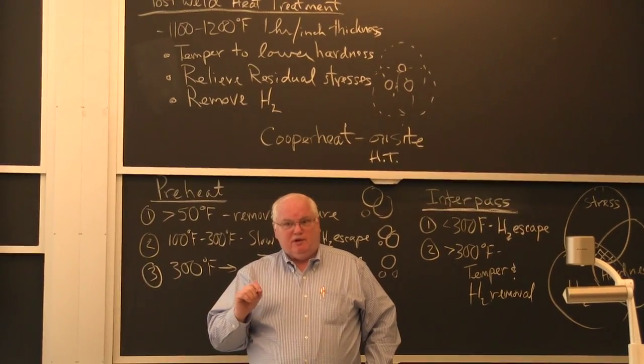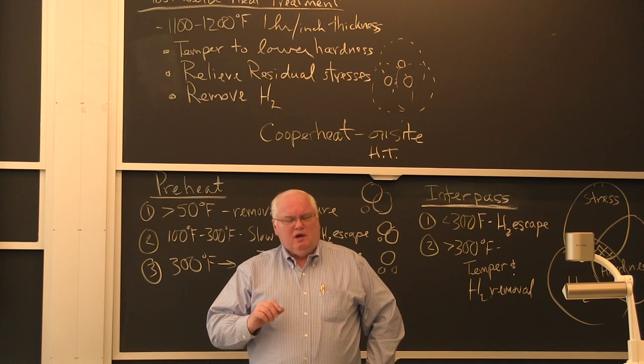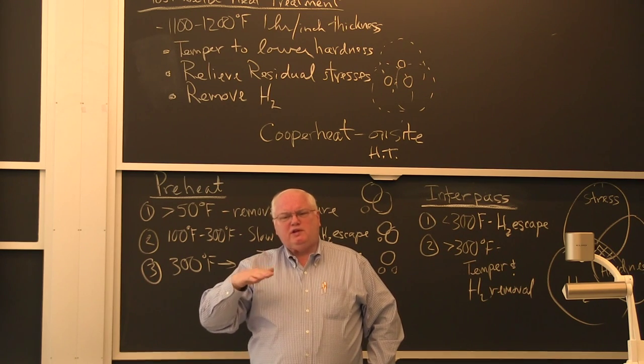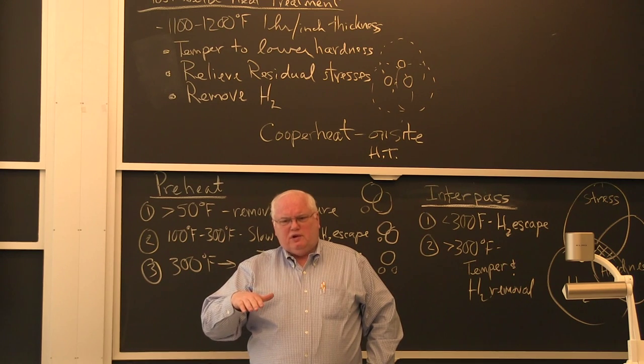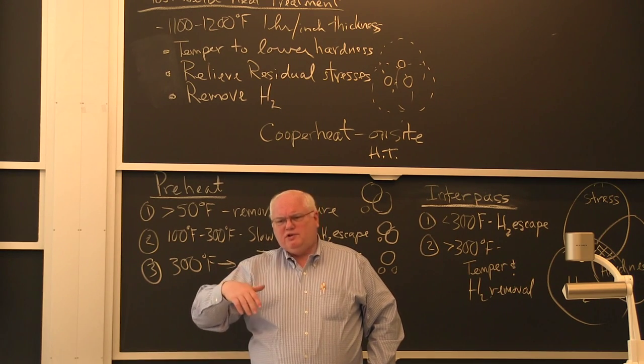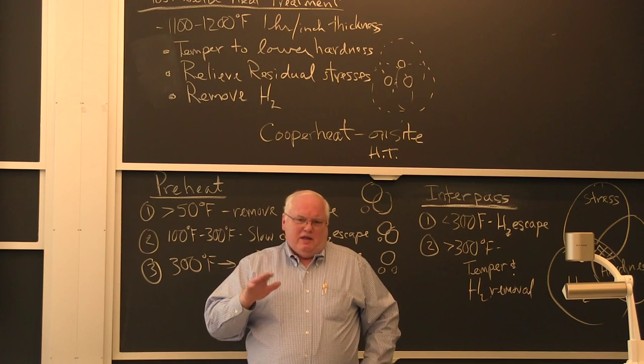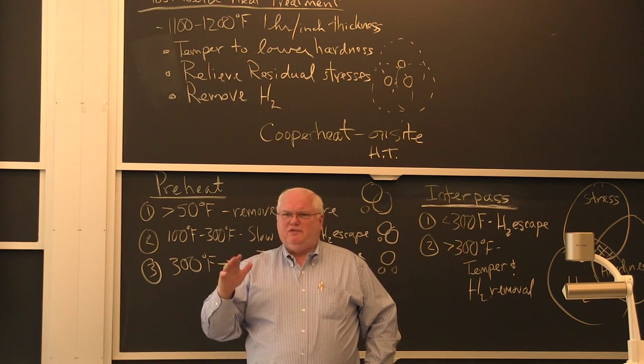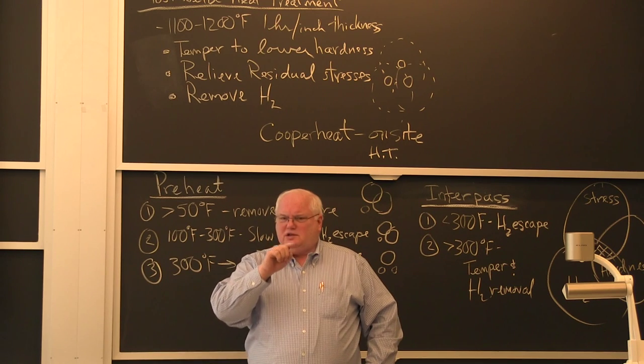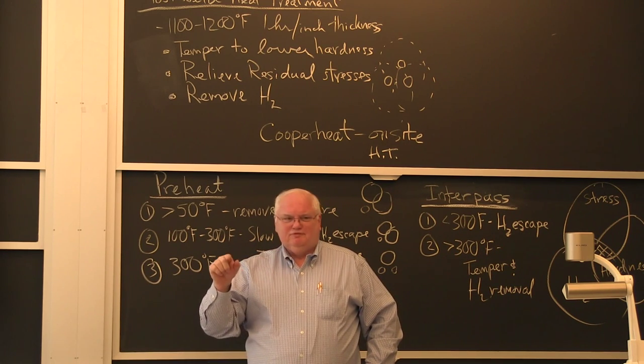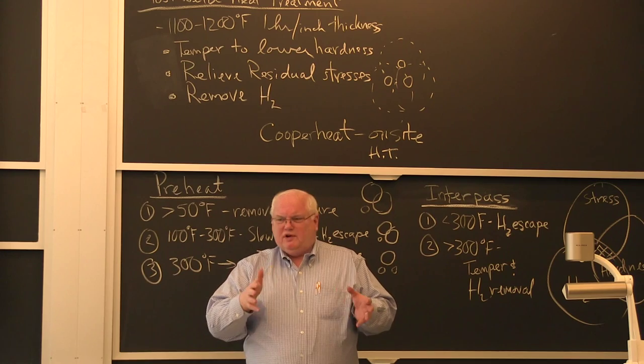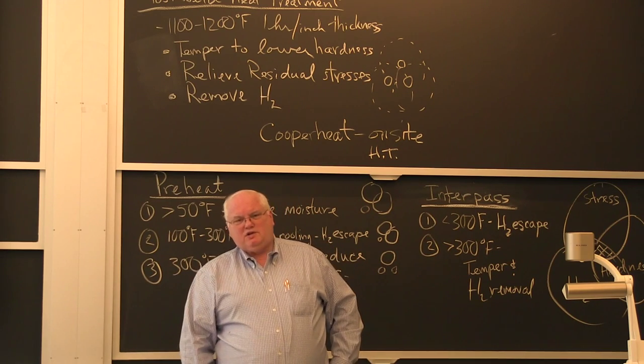Except for certain types of weld geometries like a fillet weld at inch and a quarter. Some welds at inch and a quarter you don't have to stress relief, some welds at inch and a quarter you do. At one and a half inches you pretty much always have to stress relief. So it depends on the geometry as well and they have these rules. It's UCS 56 I think is the table. UCS means unfired carbon steel, 56 is the table in that section for how to design unfired pressure vessels in carbon steel.